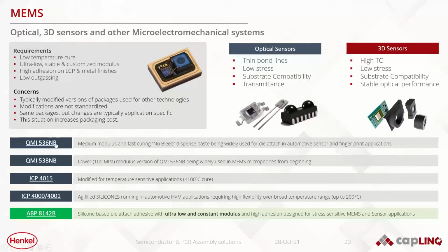So if you take a look at traditional materials that have been used, this is the QMI536NB. The NB stands for non-bleed, and this is a Teflon material that's been used for a long time for these package types. 538NB is a similar technology, but is suitable for even larger dies because it has a lower modulus than the 536NB. The 4015 is a material that's been designed specifically to cure below 100 degrees Celsius. And the silver-filled silicones of 4000 and 4001 have been running in high volume manufacturing and automotive applications.